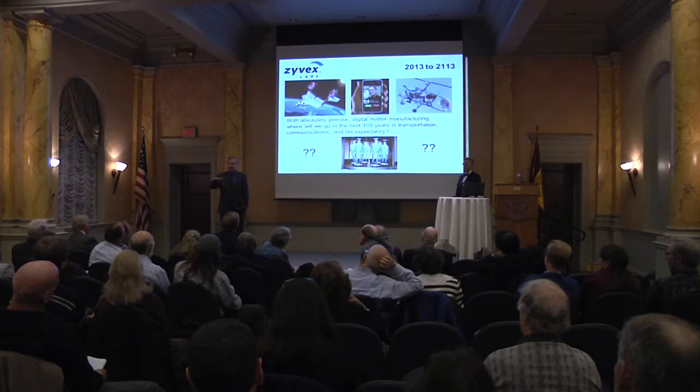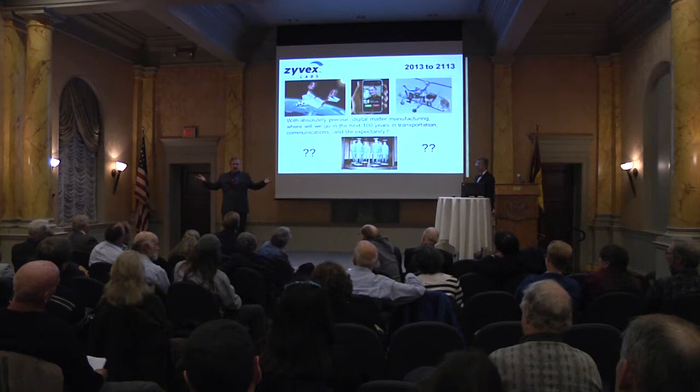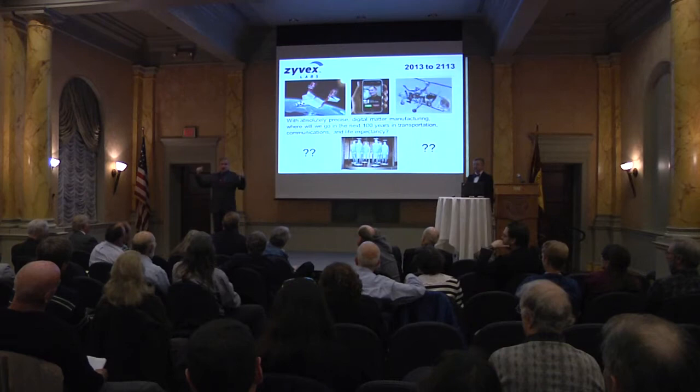But then the question becomes how long can I keep that silicon clean in UHV before I need to bring in the disilane? That limits what I can do, because the patterning is the slow part. It takes a second or two to deliver a few Langmuirs of disilane that sticks down on the silicon, or whatever else I'm depositing there. It doesn't take long at all to deposit. The length of time is patterning. So the better my vacuum, the more I can pattern before I have to dump in stuff, and that has advantages in terms of doing the lithography.